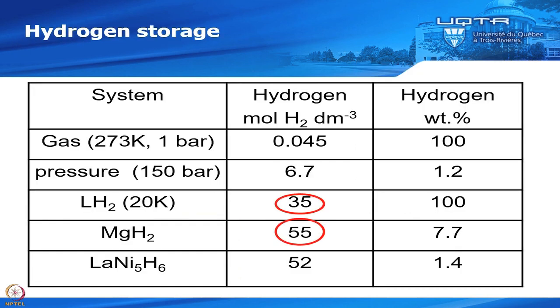So to give you some idea of the difference of metal hydride with respect to the other ways to store hydrogen. If you store hydrogen in gaseous form at 1 bar at room temperature, you see that the volumetric capacity is quite low. In order to increase that, you have to increase the pressure. So if you go to 150 bar, you have a much better volumetric capacity. If you are using liquid hydrogen, so usually if you want to transport a huge quantity of hydrogen, liquid hydrogen, in my opinion, is the best way. Of course, it's at low temperature, at 20 K, but you see that the volumetric capacity is quite good.